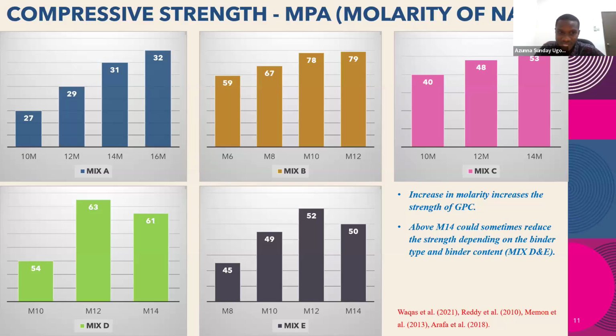So why do I say that? For mix A, for mix B, for mix C, it keeps going up as you increase the molarity, even up to 16 in some cases. Then mix D and mix E at 14 molarity, you can see that the strength came down. So now there are factors that can affect the reduction in strength at a higher molarity. One of it is the type of the binder you are using and the binder content. So if the calcium oxide is very high in your binder content and you use a very high molarity for your sodium hydroxide, you realize that